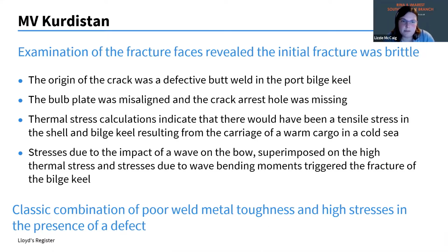That combined with impact loads on the bow meant that you had an overload of the bilge keel and it fractured. So this is a combination of poor weld metal toughness and high stresses in the presence of a defect. They didn't quite establish the sequence of the failure, but they did identify that it was due to this low temperature, high temperature transition, and the weld defects.